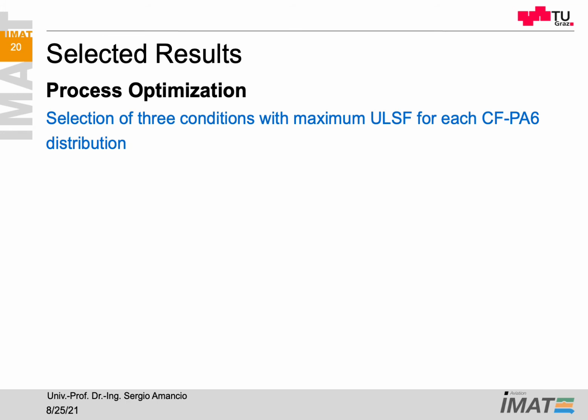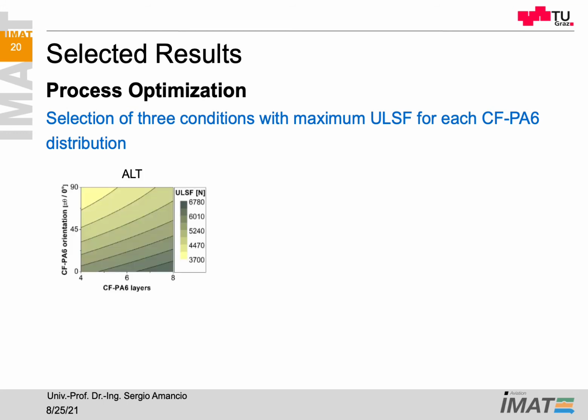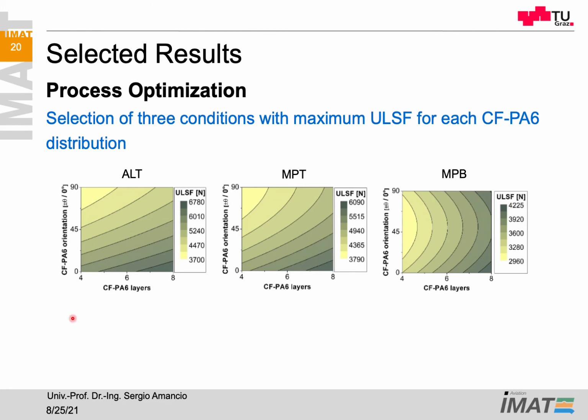So all the influences of the single variables on the ultimate lap shear force are available upon request. We published that. We can send it to you if you have interest. So let's focus on the process optimization because of the time available. So what we have here are plots between the number of layers and the orientation of the layers. And we have here in different colors the ultimate lap shear force for the alternate condition, for the middle plane top, and for the middle plane bottom conditions.